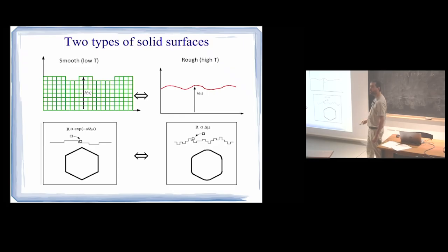It's two-dimensional nucleation. It's a slow dynamics. If, on the other hand, you are a rough interface, there are no privileged spots in your surface, and you have a nice, simple growth law. The rate of growth is linear in the saturation. So this is fast growth, this is very slow growth. Okay? So that's an important distinction.